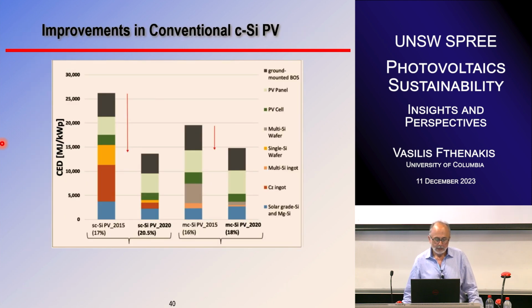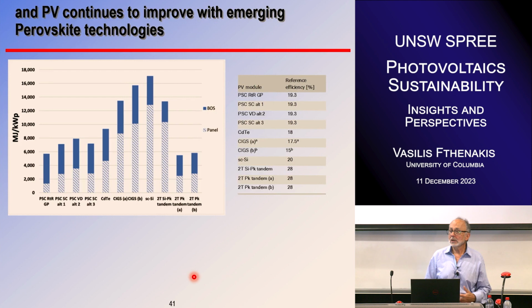As you can see here, again, for the Czochralski silicon and the wafer, there are those two colors, the dark brown and the yellow, and you can see that in 2020 they have been reduced a lot, again because of the kerf loss reduction, thickness reduction, wafer reduction, and this improvement of efficiency. And you have some reductions in multicrystalline as well. Now, with new technologies like perovskites, the situation can be even better, because perovskites, especially with solution-based feedstocks, don't use a lot of energy.